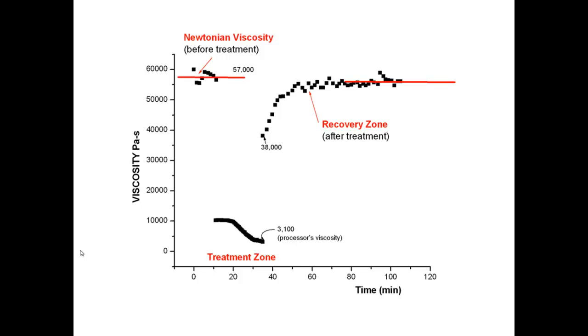What happens if I just reverse, as I said I would in step 3? I reverse the conditions back to what was in step 1, low frequency and low strain amplitude, and there is an immediate jump of the viscosity to 38,000. Well, this is not 57,000, so it does not return all the way to the initial viscosity, which would be the case if the material was just shear thinned.